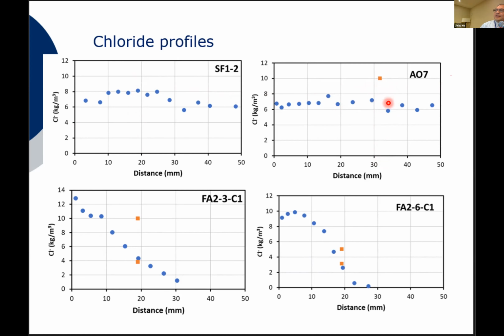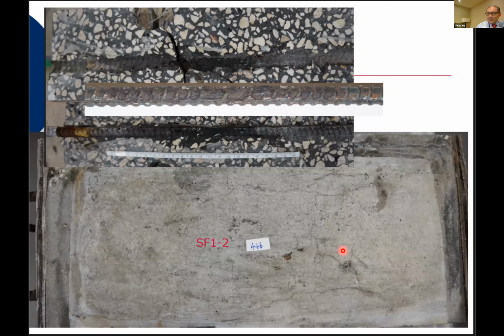And we have reported this with work that we did when I was doing my PhD with Dr. Sagüez, and also Dr. Hart at FAU has reported that the presence of the rebar actually increases the concentration that you find on the rebar trace right above the rebar compared to what you observe from a core. And okay, so let me go really quickly on some of these results.